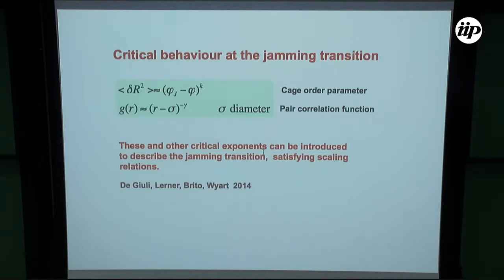At the same time, the pair correlation function at the jamming transition behaves as r minus sigma to the minus gamma, where sigma is the diameter. So what you understand from this type of critical behavior is that there is suddenly some sort of jammed state where a macroscopic number of particles starts to touch each other and form this jammed configuration. So these are just two of the many critical exponents which can be introduced to describe the jamming transition, which satisfy scaling relations, described very nicely by De Giuli, Lerner, Brito, Wyart some time ago, and also other people, of course. So this is the jamming transition.